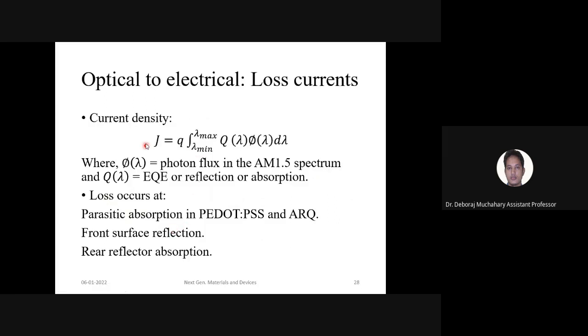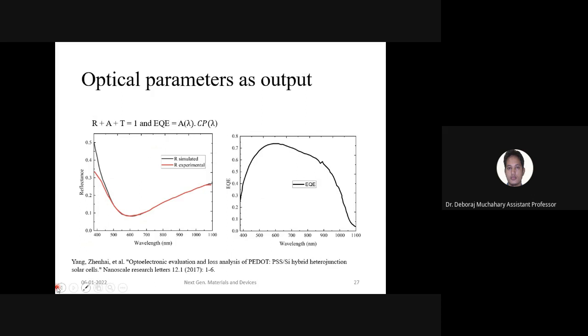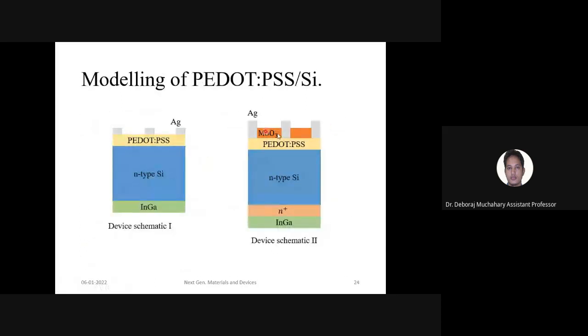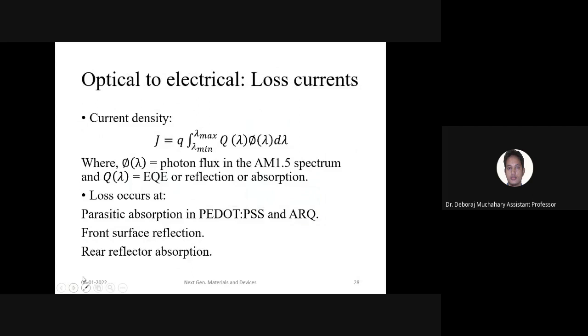Now when you have different layers, like in this structure, let me go back. In this structure you have different layers. So absorption here is different, absorption here is different, so recombination loss here is different. If you want to individually check the absorption in the different layers, you can use this type of equation, where q phi is the photon flux, and q is the EQE. You have the EQE or reflection profile or absorption profile, then you utilize those values here and integrate within the range of the wavelength, and you will find the corresponding current. So these things you can analyze.